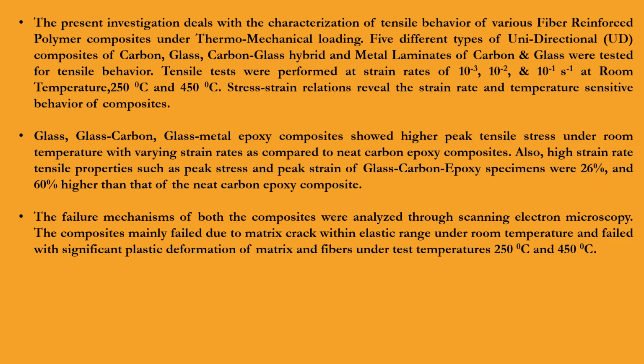The failure mechanisms of both the composites were analyzed through scanning electron microscope. The composites mainly failed due to matrix crack within elastic range under room temperature and failed with significant plastic deformation of matrix and fibers under test temperatures of 250 degrees Celsius and 450 degrees Celsius.